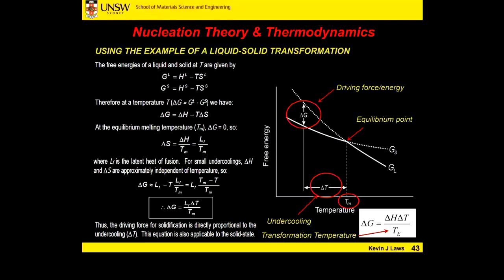in a natural system, and you've got to think about thermal conductivity and all these kinds of things, something with a higher melting point is basically more difficult to undercool. Sometimes in nature, it's usually relative to room temperature or the temperature of your mold or whatever you're using. But for just a general representation, I think this equation here covers it. This is basically our delta H factor, which is constant for a given system. This is a chemical dependence, and then we've got our undercooling and our melting point. This is going to be constant. This is going to be constant. Delta G proportional to delta T.